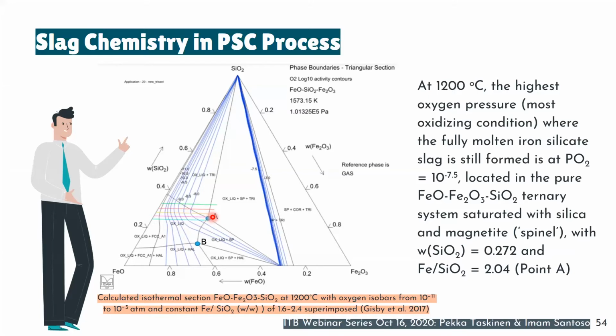If we use a higher oxygen pressure, for example, in here, minus 3, we don't have liquid slag anymore because the slag is in here. So the indication that the process is good, we can see from the slag that contains silica and magnetite, because point A is a slag in saturation with silica and magnetite.